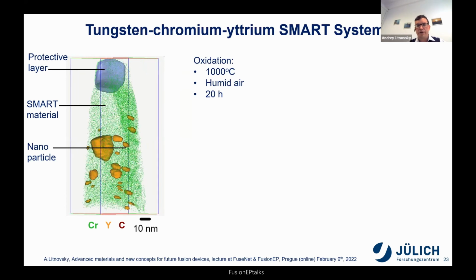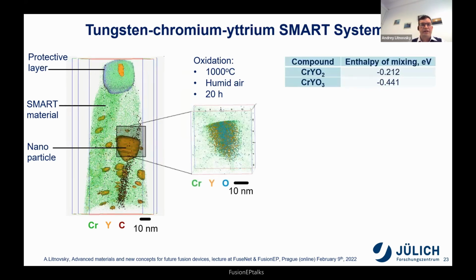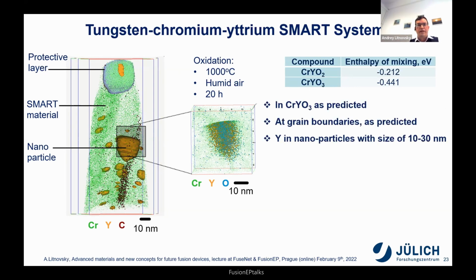We had our colleagues in Oxford and in Warsaw, who simulated for us these effects. What we found, experimentally and with modeling, is that the oxygen, here in blue, is only within the yttrium particle. So yttrium plays a very important role, being a very tiny amount. It sucks like a vacuum cleaner. All the oxygen cleans the boundary and makes the so-called perovskite-like mixed oxides, which are shown here. And there was tremendous agreement between the modeling and experiment. So the yttrium was found experimentally in this particular stoichiometry exactly as predicted by the modeling, at grain boundaries as predicted by the modeling, and in very tiny particles.